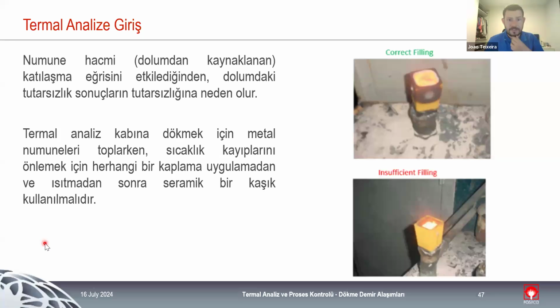Yes, the only thing that I can say regarding this is to always have the same amount of metal in the cup. So every time you are doing thermal analysis studies or you are doing thermal analysis during production, always use the same cup, because the amount of metal that you put in the cup can interfere with the calculations that the system does. So all the calculus that the system does related to carbon content, silicon, carbon equivalent, it is based on the amount of liquid metal that we use inside the cup. So the way to stabilize the cooling curve is to always use the same conditions, so the same amount.